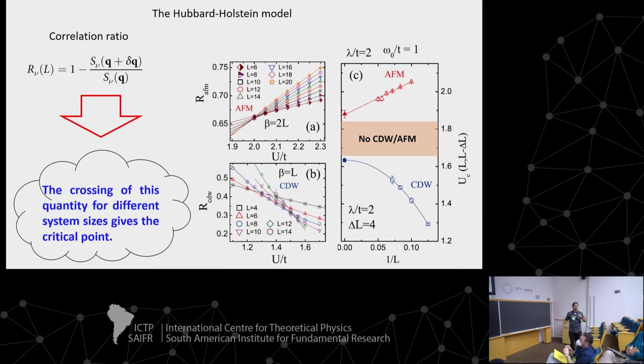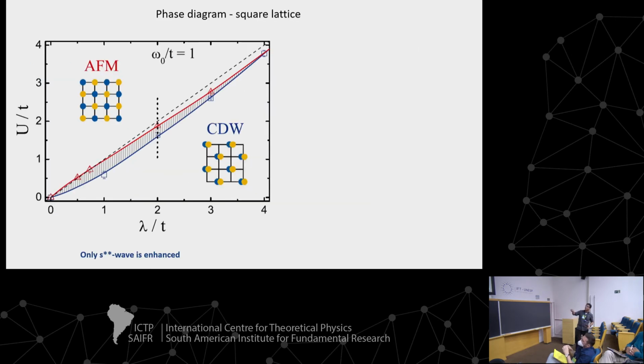Is the next... yes, exactly. The Q here is the dominant wave vector, and delta Q is just the neighbor. Yes. And so here we can perform a finite size scaling analysis in order to see it in the thermodynamic limit. And we see that, for instance, for a given value of parameters, we have one region where we have antiferromagnetism, a region that we have CDW, but there is a region in the middle that we don't have neither CDW nor antiferromagnetism. And if we perform this analysis for many other values of parameters, we are able to create this phase diagram here.